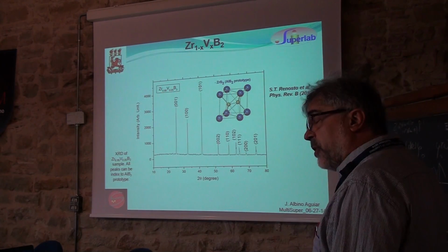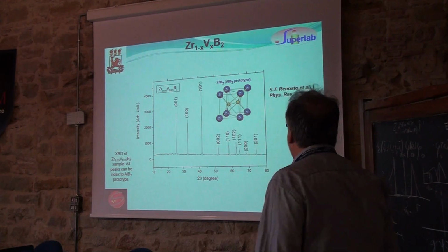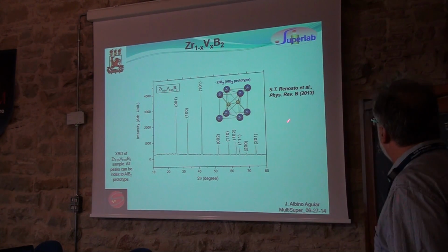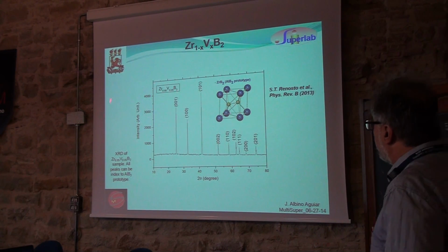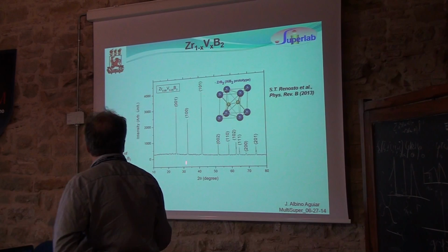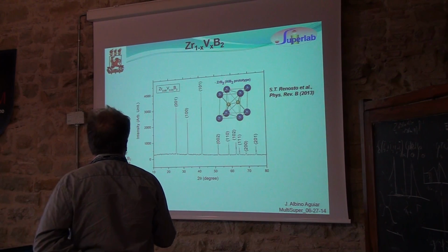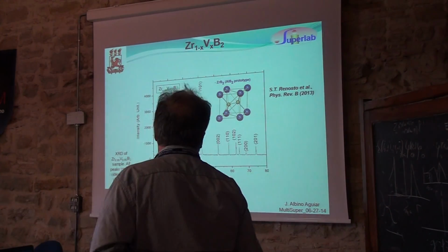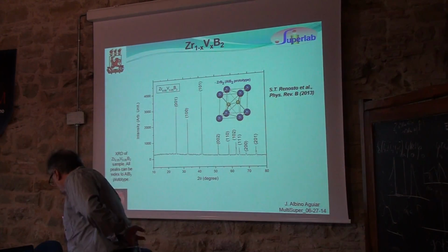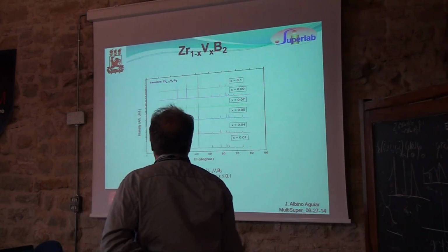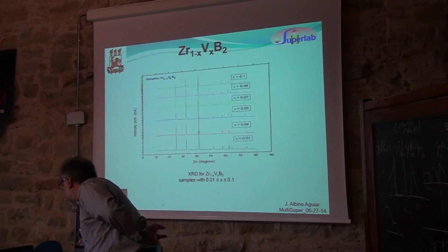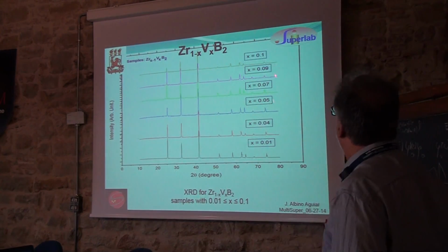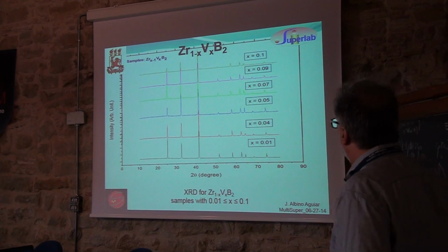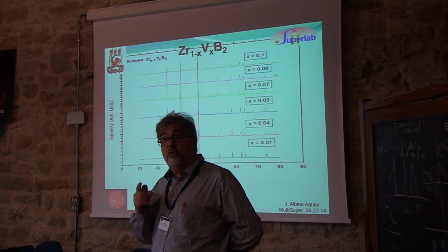So here is the X-ray for zirconium 0.95, vanadium 0.05. This was published last year, and you see that we can index all the peaks in the aluminum boron 2 prototype. For all concentrations we studied, we can zoom here, and we have the same structure. So we see no trace of zirconium boron 12. This is very important.